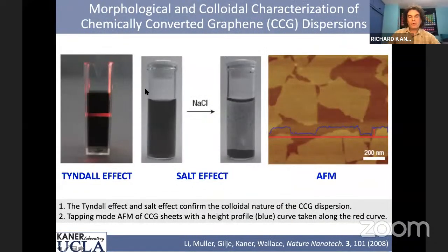So first, a little bit more about taking graphene oxide and chemically deoxygenating it. So one of the first experiments we did is we simply put the graphene oxide in hydrazine, to bring it back to a form of graphene. And it disperses in water, and it shows the Tyndall effect. The Tyndall effect is if you shine a laser through it, if it were a solution, the laser would go right on through, but in fact, it scatters light, and you can see the red laser here. And the reason it does this is because you have individual sheets of carbon with a negative charge. And so they all stay apart from each other and they stay dispersed in the water.